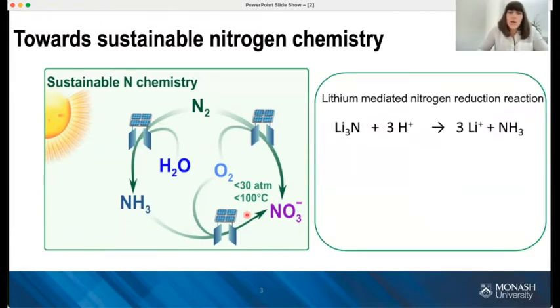Among investigated modes of the nitrogen reduction reaction, a lithium-mediated process appears to be the most promising. And the mechanism of that process, which is shown here, is hypothesized to rely on a cathodic reduction of lithium ions in the presence of nitrogen to form lithium nitride. And this lithium nitride is then reacted with the proton source to form ammonia molecule. So ideally, those protons would come from oxidation of hydrogen or water on the anode, and then be transported by a proton shuttle molecule to the cathode, where this process would occur.